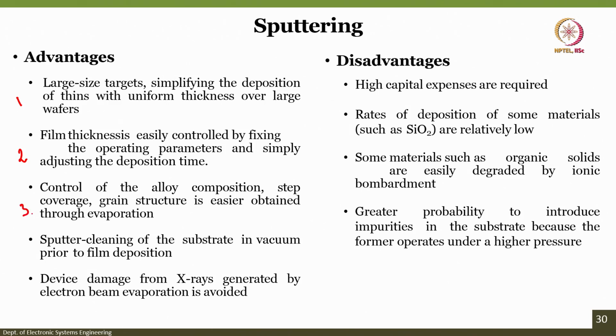Sputter cleaning of the substrate in vacuum prior to film deposition is possible. That's a very big advantage because then none of the material that was present earlier will still be there. We can just clean the chamber right before we start a new deposition. That is advantage number four. Finally, the device damage from X-rays generated by electron beam evaporation is avoided. This is very important, because e-beam will cause X-rays to be generated, which will actually deteriorate the film. Compared to e-beam, sputtering is better in this area.